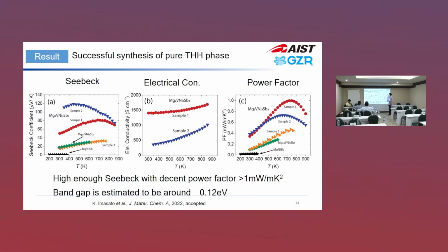so kind of small, but still a small band gap. And decent electrical conductivity leads to a power factor of 1 milliwatt per meter Kelvin squared, which is also not super high, but decent, I would say. Good materials can reach 3 or 4, so this is not reaching the best performing materials, but not a disappointing result, I guess.